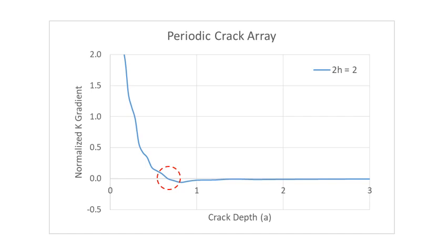So that represents exactly the point where we're going to stabilize our crack and we would expect to get no further growth. We see from the curve that if there were further growth, we would have negative K gradient, and that's just not reasonable. Unless, of course, we were to have a crack that was going into an increasingly brittle material, which is not something we're going to think about too much here.